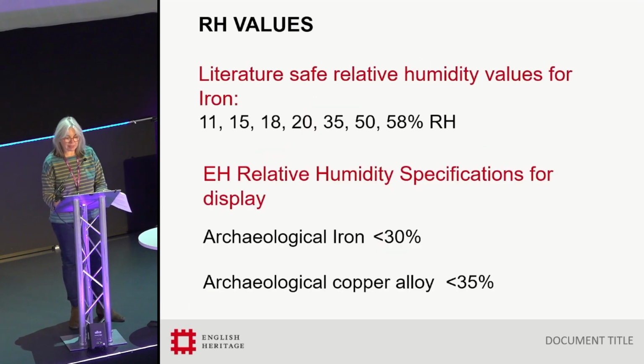Looking at published data on safe relative humidity values for archaeological iron, we see a huge range. Some of them appear at the top of this slide. Our conservation scientists recommend that our archaeological iron is displayed at less than 30% relative humidity, and archaeological copper alloy at less than 35%. These parameters are what we aim at when iron objects or copper alloy objects are being displayed without other objects made of other materials, and where different RH parameters are recommended.